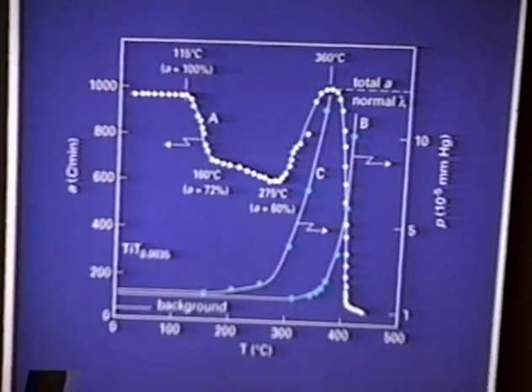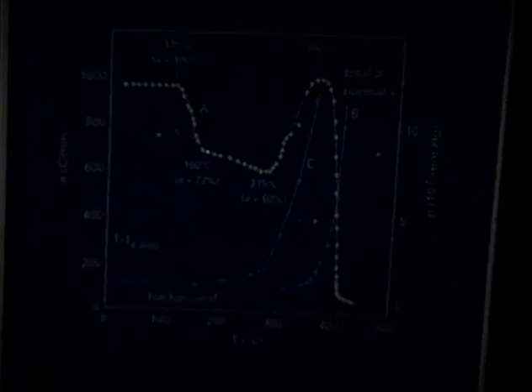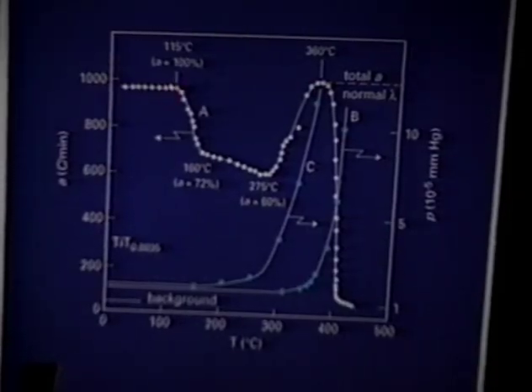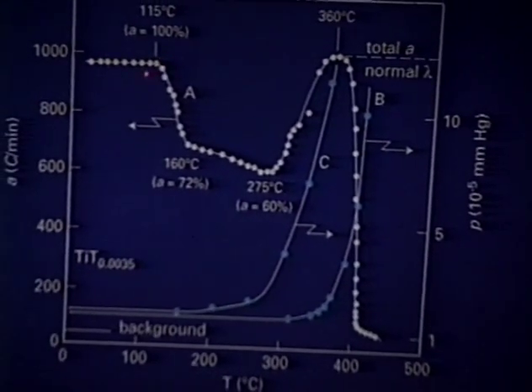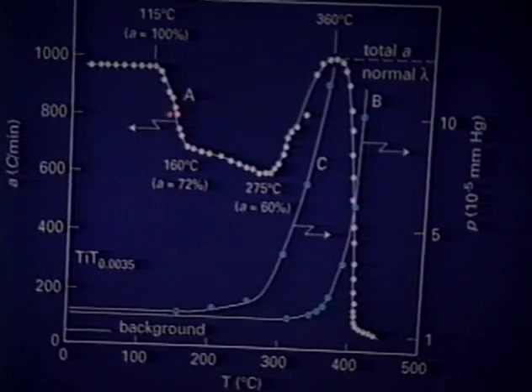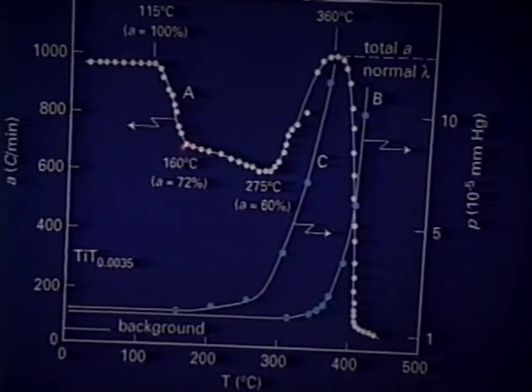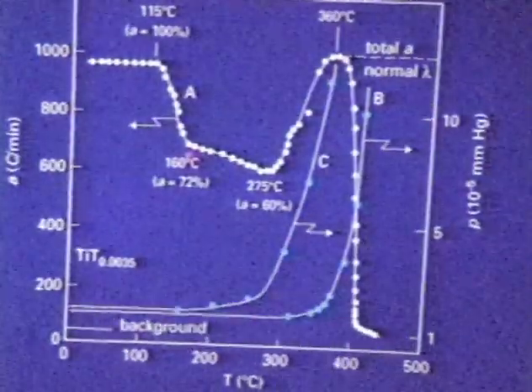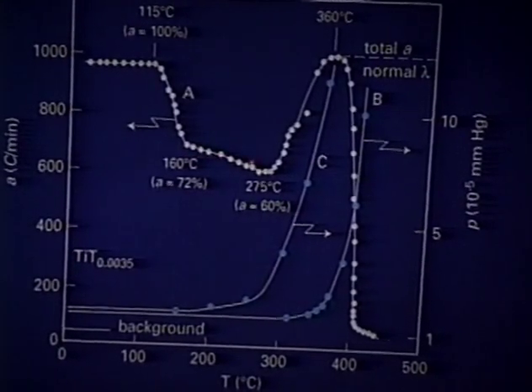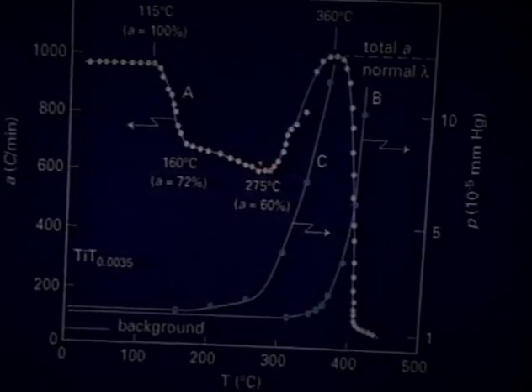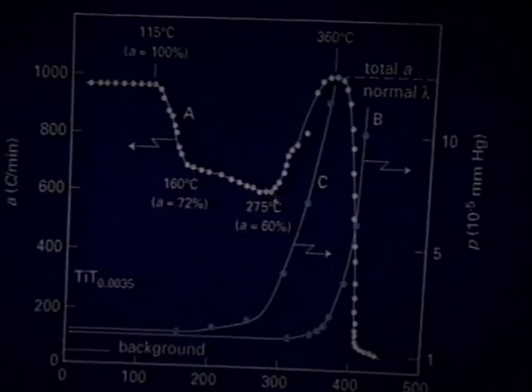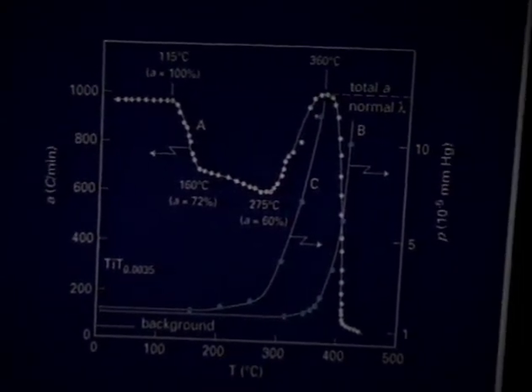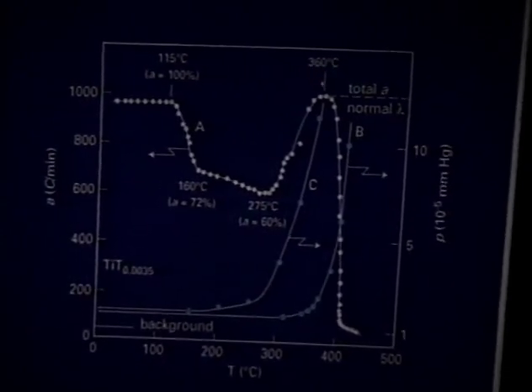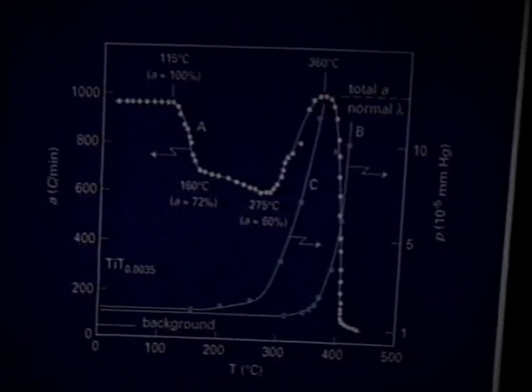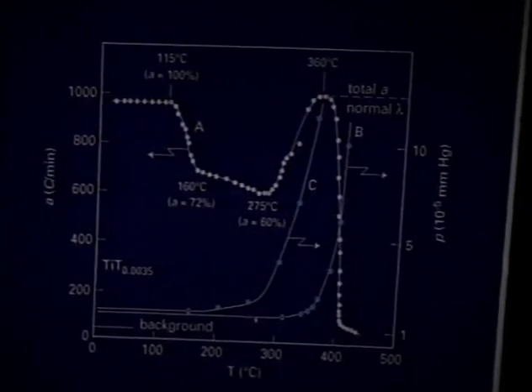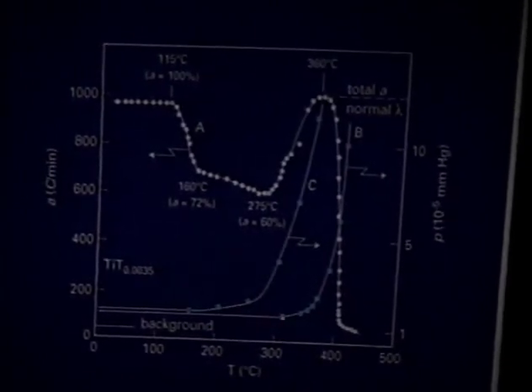Graph A gives the count rate as a function of temperature. It is very strange that at a temperature of 115 degrees centigrade, the radioactivity decreases sharply and reaches at 160 degrees centigrade 72% of the initial value, followed by a slower decrease and reaching 60% of the initial value at 275 degrees centigrade, and then it increases to the initial value, reaching it at 360 degrees centigrade before the decomposition of the preparation. We see also the decomposition of the preparation with the increase of temperature, as in the first experiment.